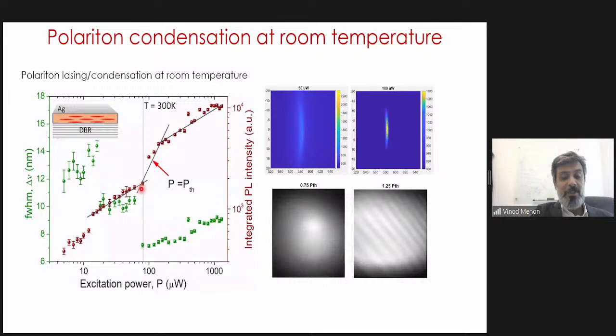So this threshold is actually a threshold where we're getting onset of condensation in this system. And so you can see here, this is in momentum space. This is the distribution in momentum space. And then you go above the threshold and everything collapses in K space. But what is really the telltale signature of a condensate is the fact that below threshold, you do an interference experiment and you see that there is no interference pattern. And you go above threshold and you get this beautiful interference pattern with a spatial coherence length extending about 20 microns. And mind you, this experiment is done at room temperature.